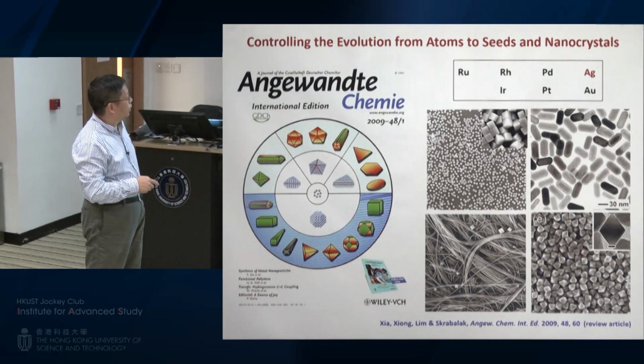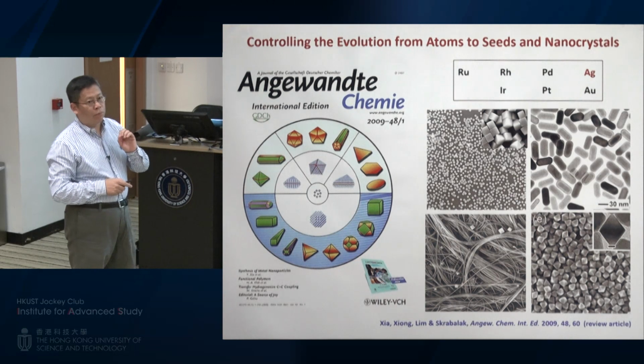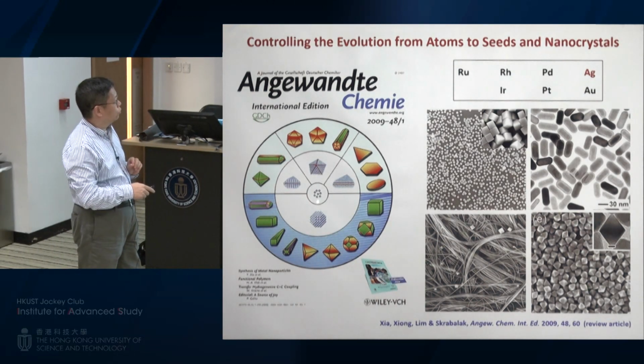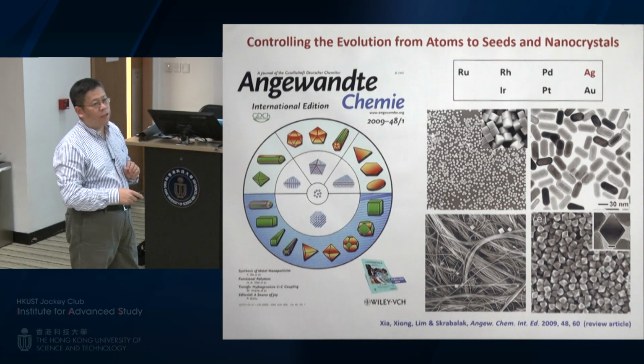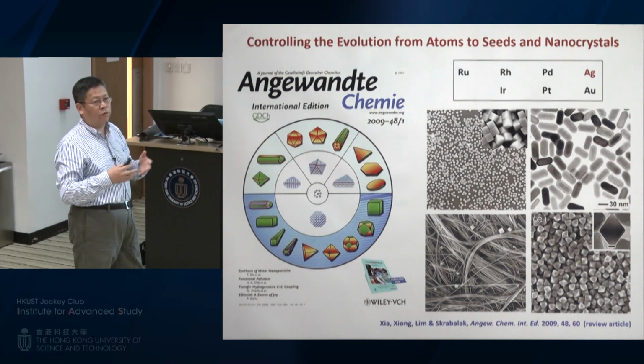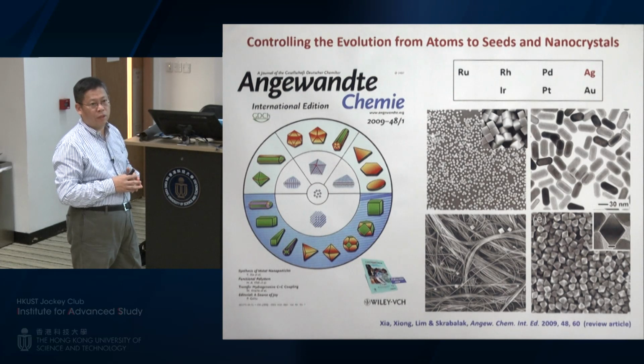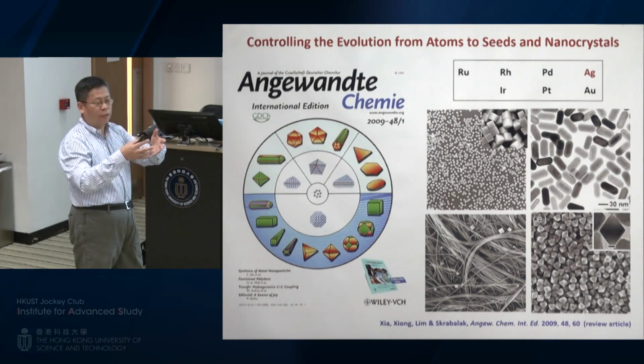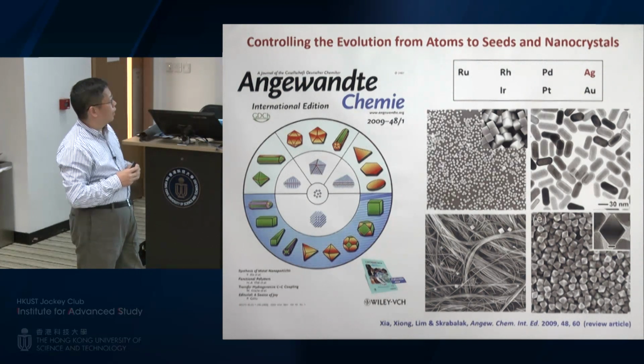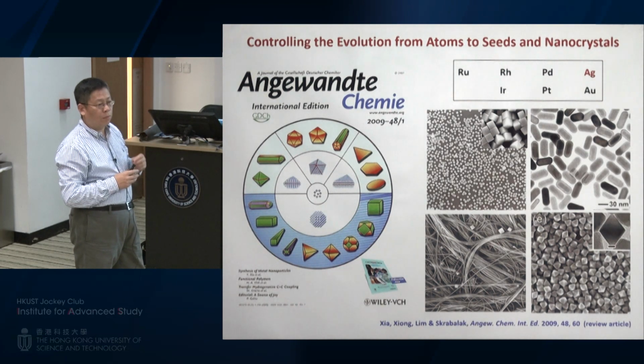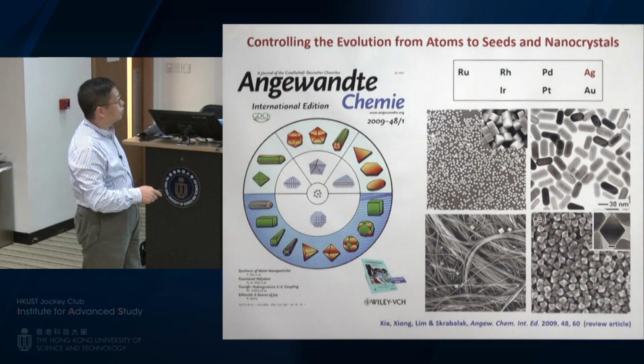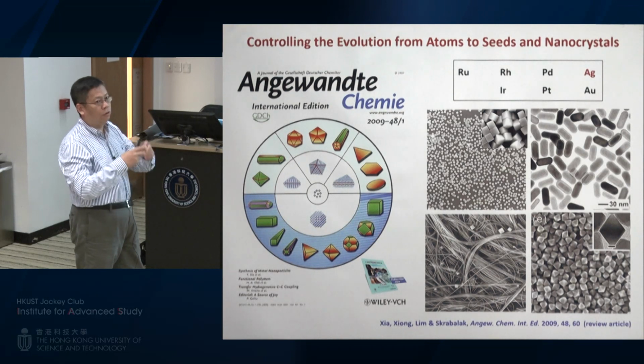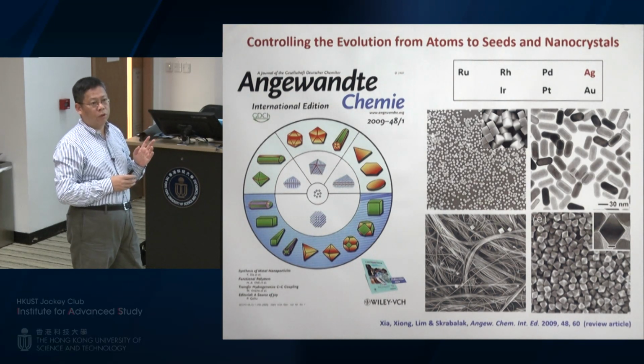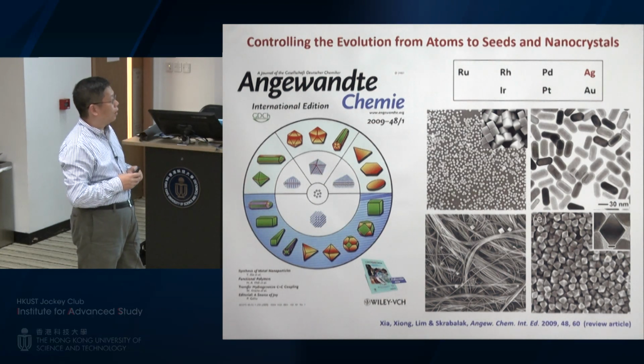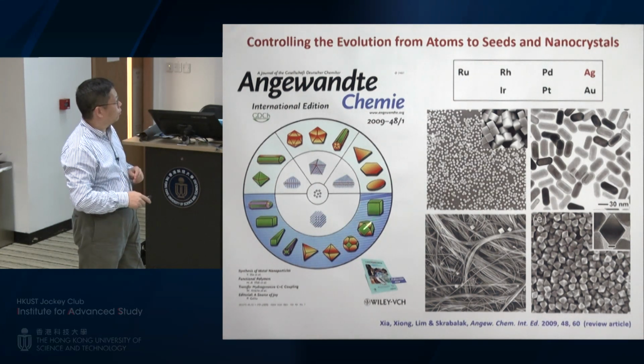And it's also clear, okay, if you want to make the purest sample, you have to have good control over both nucleation and growth. And typically for nanoparticle synthesis, people like to use one-pot approach. You have nucleation and growth basically in the same system. But unfortunately, that may not give you the purest sample, because as we know, the condition we need to make one particular type of seed could be very different from the condition you need for growth. So that's why one-pot growth in general is not the best approach to pure samples.